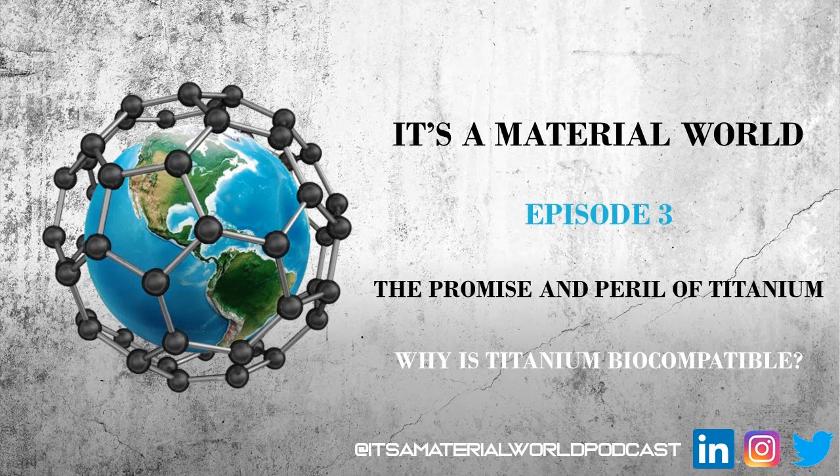A little correcting here: commercially pure titanium also has a home in the body. Ti-6-4 is higher strength by a substantial margin — almost 2x over pure titanium. Ti-6-4 and CP-Ti, commercially pure titanium, share the same reason for being biocompatible, and a lot of it has to do with the oxide layer formed on the outside of the part.